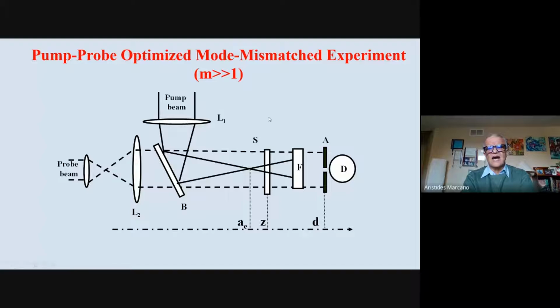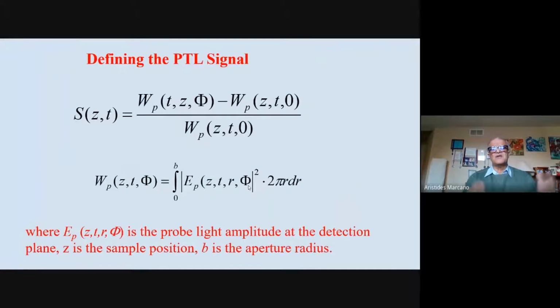And in this case, the size of the probe beam in the focal point is much bigger. Much bigger, I mean thousands of times. This coefficient m, which is the square of the relation between the radii, could be about 2,000, 3,000, maybe more than that. So people just do m equal 50, but you can do very, very big. That makes sense. And then you define your signal: the energy you detect passing through the aperture when you have the thermal lens, minus the energy when you do not have the thermal lens, divided by the energy when you do not have the thermal lens effect.